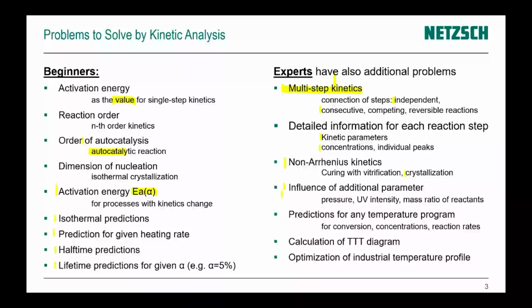Sometimes not only the temperature plays a role for kinetics, but also the pressure. For example, the rate of a chemical reaction depends on the ambient pressure of an inert gas, or it could be the partial pressure of an active gas, for example, the partial pressure of hydrogen or oxygen. For photopolymerization, we have an additional parameter, the UV intensity, the intensity of UV light. The higher the intensity, the faster the polymerization. If you have two-component reactions, then the mass ratio of the reactants plays a role, and kinetics depends on the ratio of masses of both components.